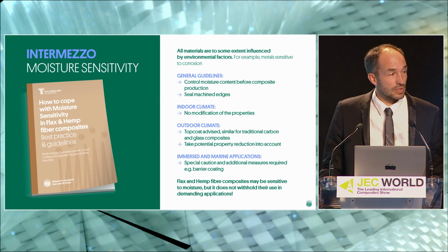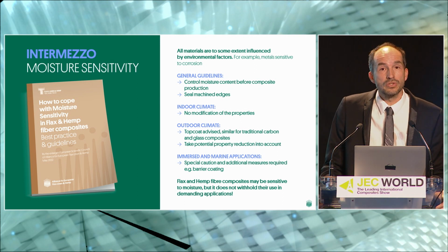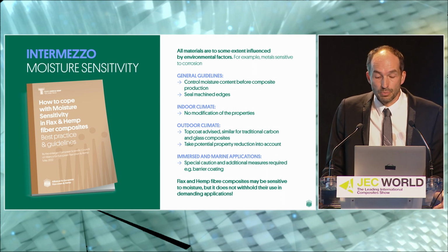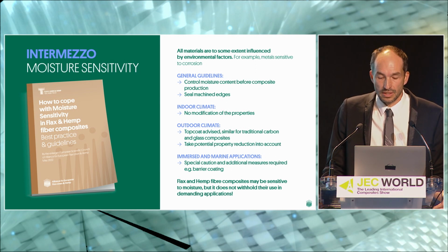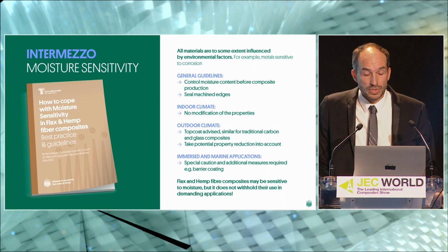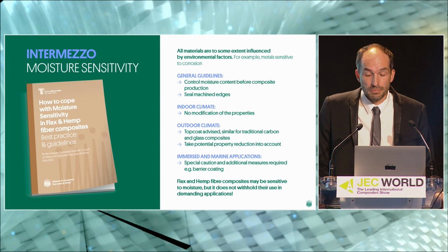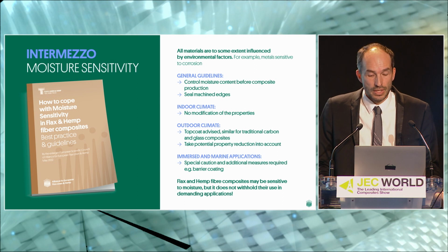And for immersion, as it was mentioned in the previous examples, it's advised to take special cautions and additional measures like a barrier coating to limit the moisture diffusion in the material. So as a conclusion, I would say that flax and hemp fiber composites may be sensitive to moisture, but it does not withhold their use in demanding applications.